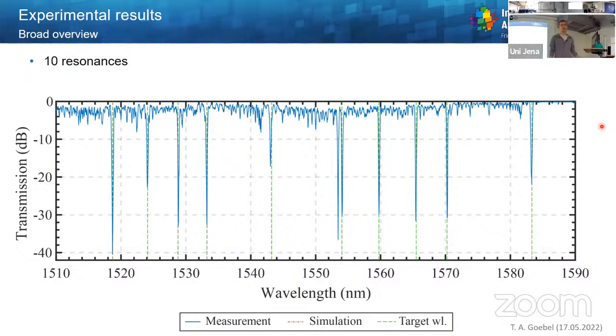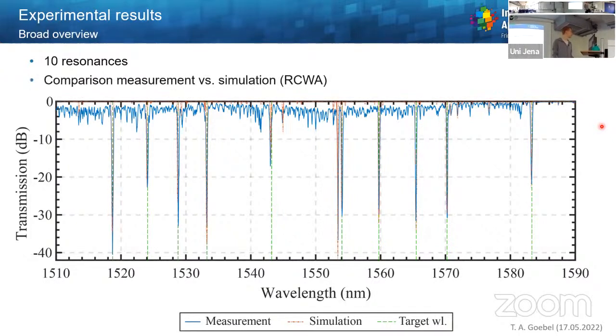So what we did is we analyzed the grating structure a bit further by a simulation called rigorous coupled wave analysis. And if we do so, we see here now with the red dotted line that we also get from the simulation intermediate peaks, not only the 10 resonances we want to have, but also some in between.